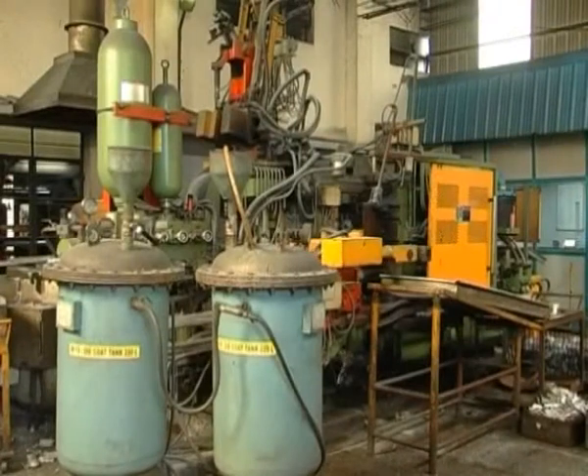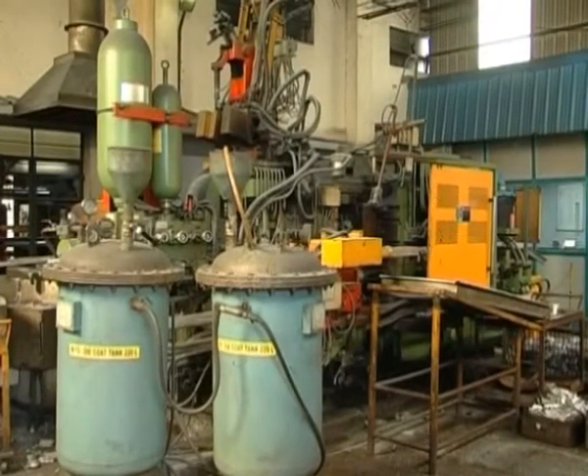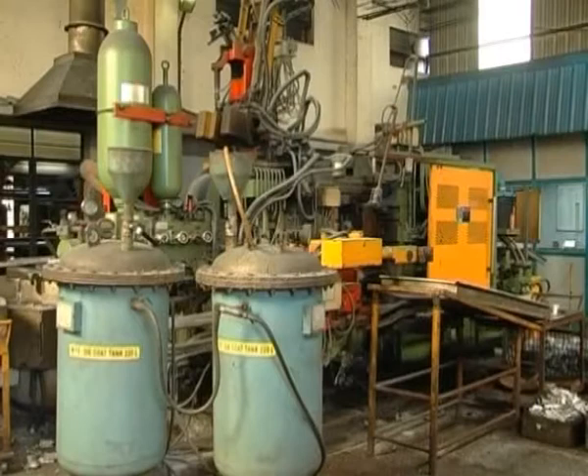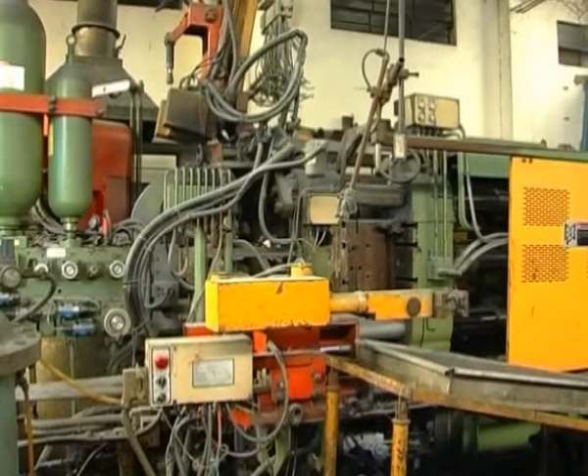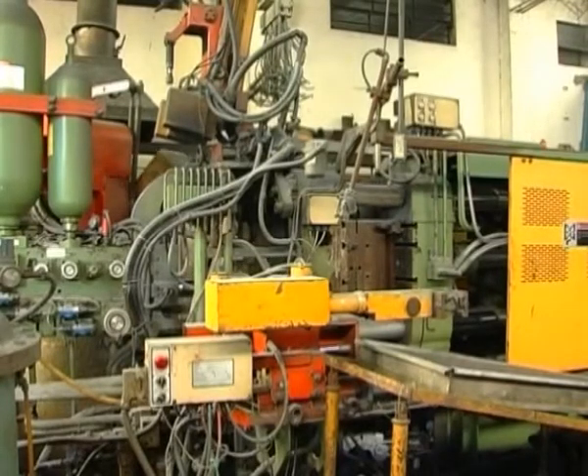French chalk or calcium carbonate suspended in sodium silicate binder is commonly used as a coating for aluminium castings. Chills are pieces of copper, brass or aluminium and are inserted into the mold's inner surface. A chill is commonly used to promote directional solidification.